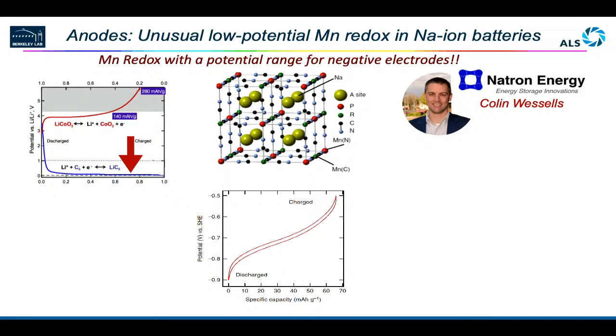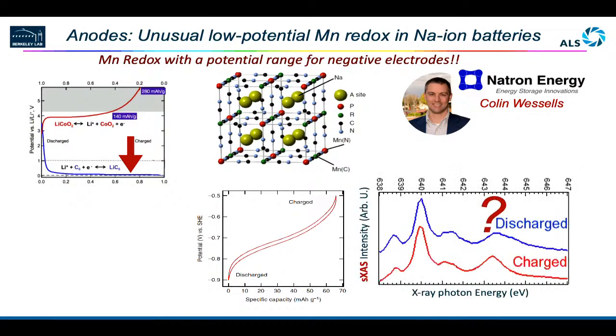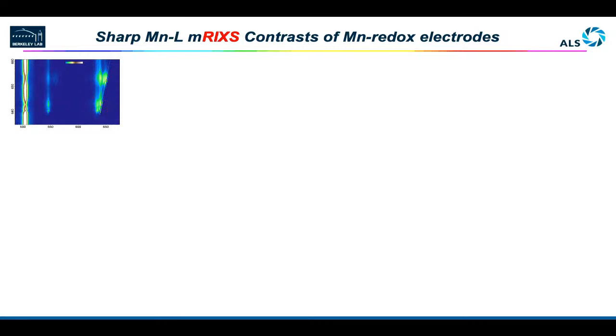And the benefit of that is in commercial battery cells, these two electrode materials are always completely different. Typically, one is graphite-based, the other is transition metal oxide-based. But if you can process both electrodes in the same type of material for industry, that's a huge gain because it reduces the material processing cost significantly. So this company is actually shooting for low-cost batteries. That's why they care about a transition metal-based anode to reach a very low voltage. However, the material itself was already manganese 2+, and if you reduce it, on the X-ray absorption you really don't see the charge and discharge. You barely see a little difference here, and then we want to go a step further using RIXS to see whether we can really differentiate the charge and discharge.